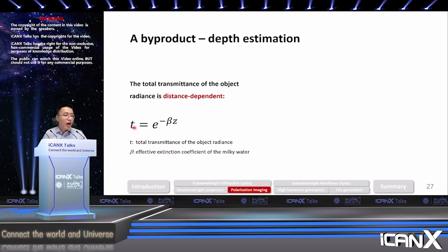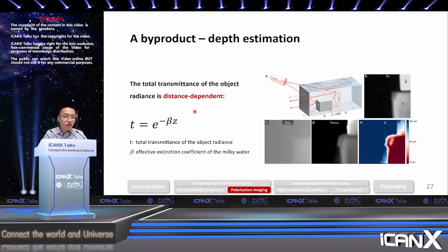From this polarization analysis, we are able to retrieve the value of T, and if we can fit the extinction coefficient of this milky water, we are able to render a depth map. In the experiment, we put two objects at different Z positions, and by doing this polarization analysis, we are able to estimate the depth of each object.